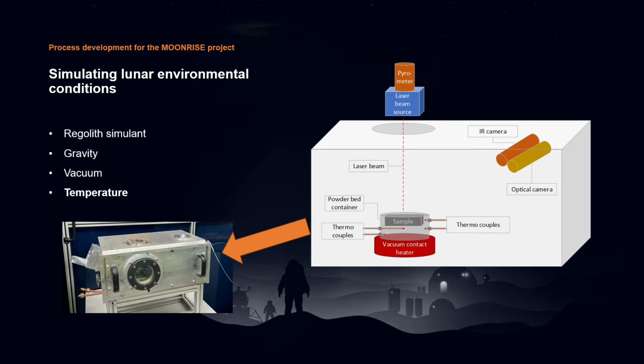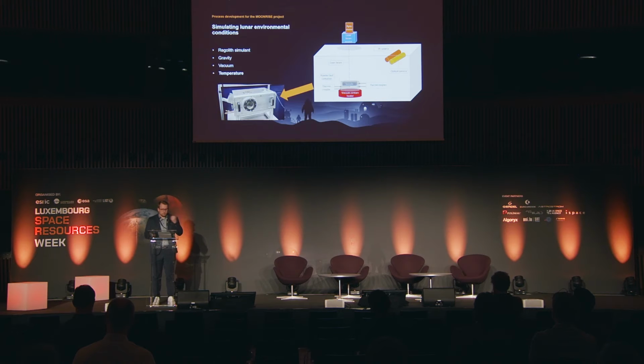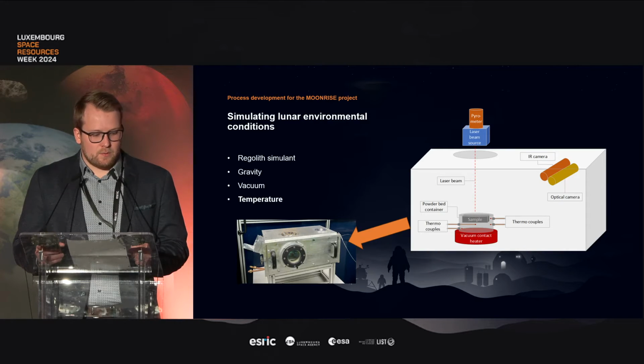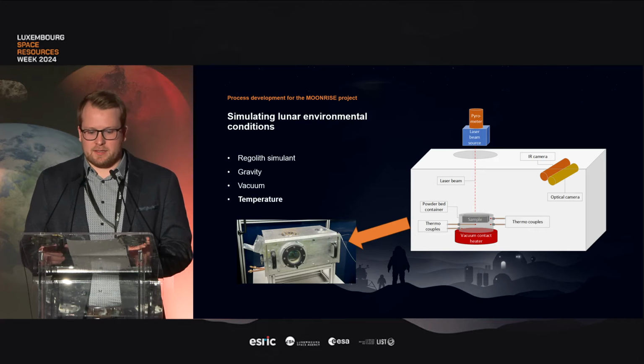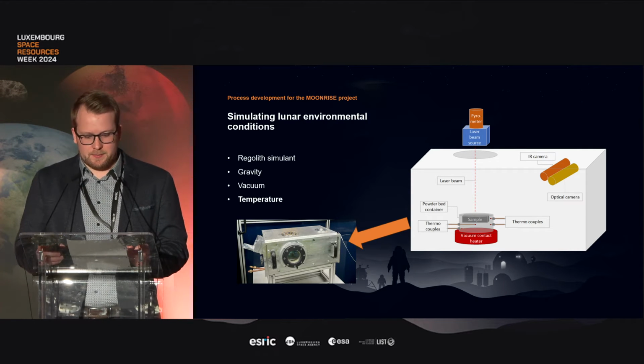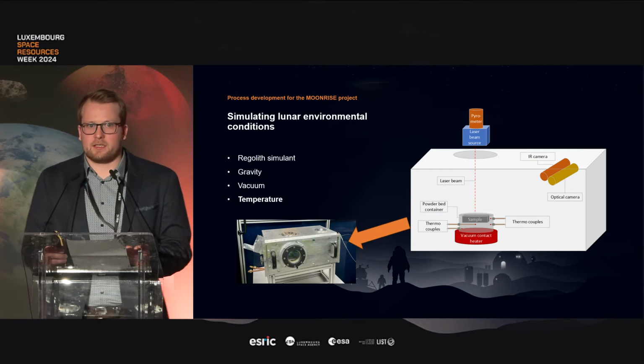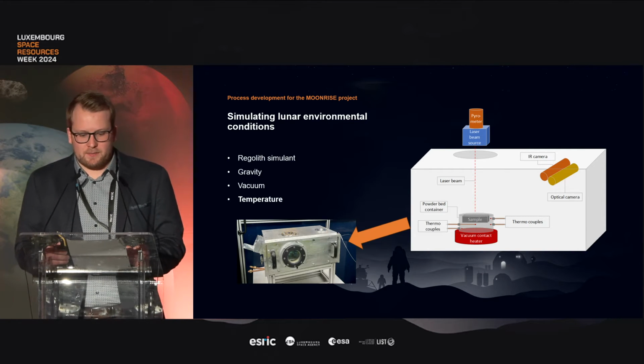Below that, we will have our powder container with some thermocouples in there to measure the temperature in the powder bed. And below that, we will have our vacuum contact heater. With that heater, we will generate temperatures between room temperature and around 150 degrees Celsius. So we can only monitor temperatures that are above room temperature. And we will also add some infrared cameras and an optical camera to see the behavior of the process. And with all of that combined, we can start developing our process strategy for the moon.